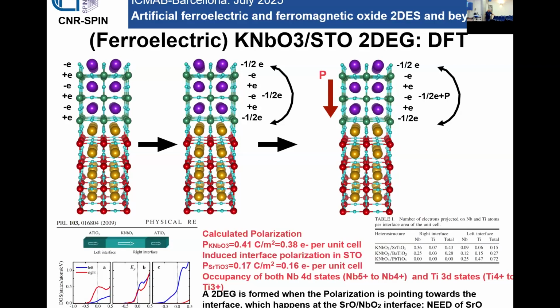description of the system. Luckily enough, there are also DFT calculations. The systems are quite old. In 2009, there were DFT calculations exactly on that system, considering essentially 2 kinds of interface. One is the interface between strontium oxide and niobium oxide, so the interface which favors the formation of 2DEG, and the other one, the opposite interface.